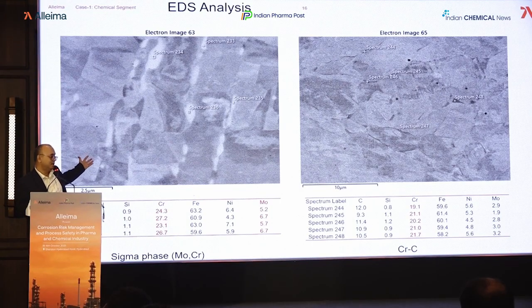You can see on the left-hand side something bright at the grain boundary. That bright phase is what we generally call the intermetallic, and it varies from grade to grade. There you have basically chromium and molybdenum. Those are very, very important, as they give you the corrosion resistance. And then you have segregation of those phases at the grain boundary. What may happen is that overall your chromium and molybdenum percentage will reduce in the alloy, and your corrosion resistance will decrease. That is the harmful effect of this intermetallic phase formation.